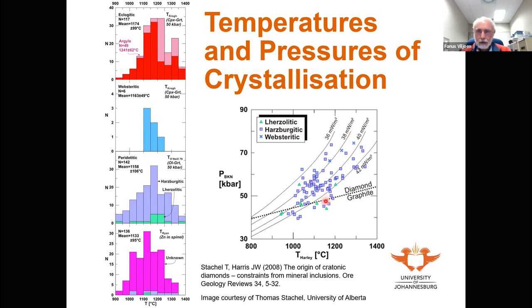If you have higher geothermal gradients, for example, more than 42 milliwatts per square meter, you will end up in a region where your diamonds, having crystallized originally, if this is a heating event, your diamond will be destroyed again. But essentially for our purposes, if you're looking at thermal gradients of about 38 milliwatts per square meter, that's where your diamonds will be stable.